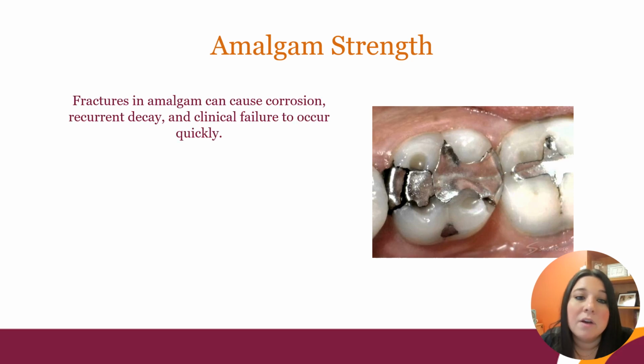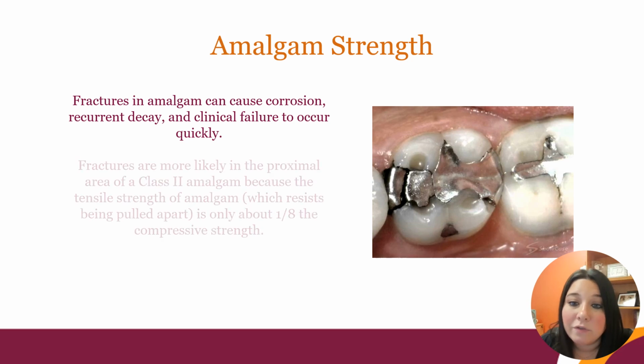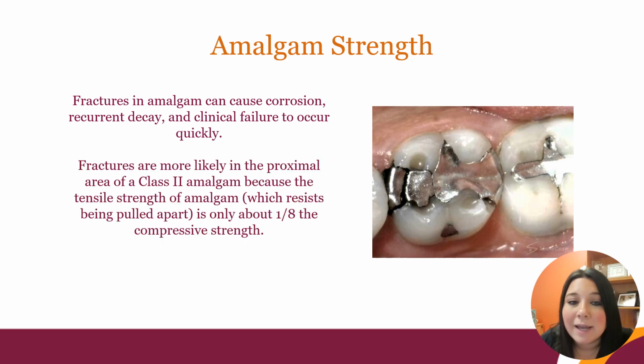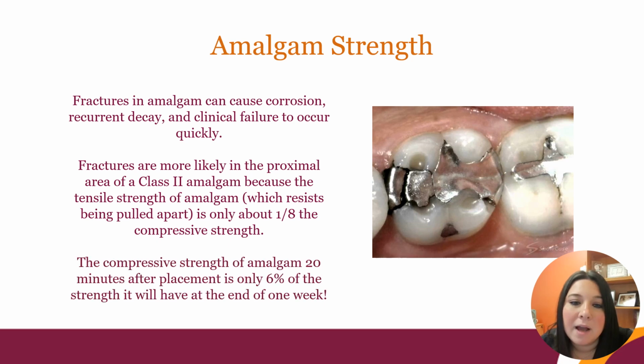Amalgam strength. Fractures in amalgam can cause corrosion, recurrent decay, and even clinical failure. Fractures are more likely in the proximal area of a class 2 because the tensile strength of amalgam is only about 1/8 the compressive strength. So you are more likely to have breakage kind of in that interproximal area where you floss between an amalgam filling. The compressive strength of amalgam 20 minutes after placement is only 6% of the strength it will have by the end of 1 week. So again, amalgam fillings aren't going to be set fully right after placement.